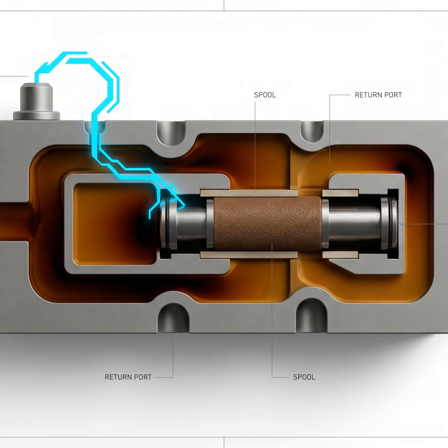The engineering data in the case study notes that even a 0.25 millimeter misalignment, a quarter of a millimeter, which is barely visible to the naked human eye, creates a massive microgap. That tiny gap allows highly viscous molten polymer, driven by 150 megapascals of force, to escape and destroy the seal. A quarter of a millimeter misalignment causes a catastrophic leak and a factory shutdown. That is wild. It highlights the extreme, uncompromising tolerances we are dealing with. You cannot guess, you must measure.